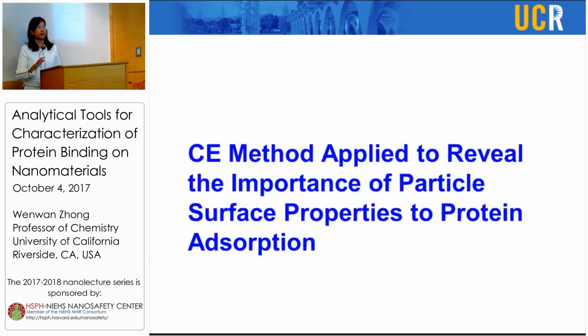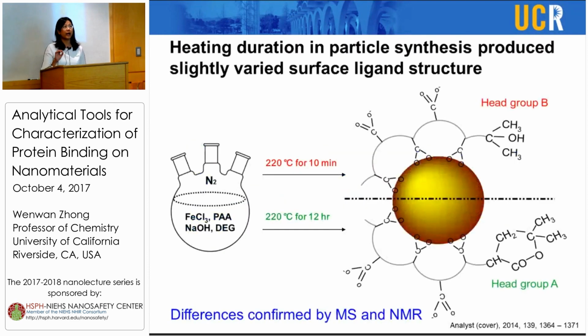So we apply this CE method to screen iron oxide interaction with a few proteins, to identify whether surface functional groups are very important in controlling protein interaction. In this project, we prepared two kinds of iron oxide particles which have identical size and the same iron oxide, Fe3O4, material, and are superparamagnetic. Their core size is around 10 nanometers, and they are both originally coated with polyacrylic acid.